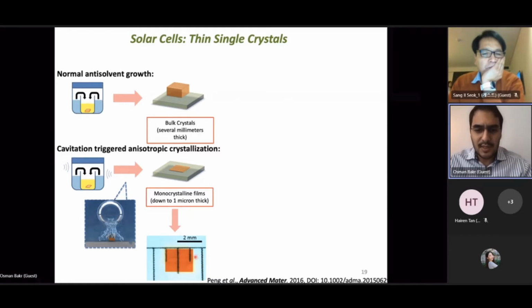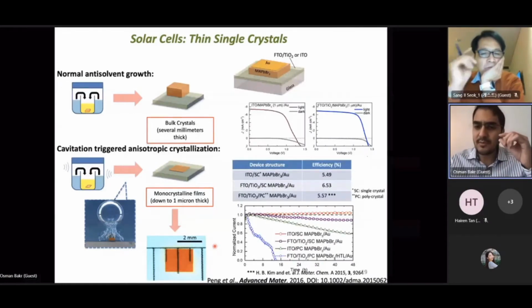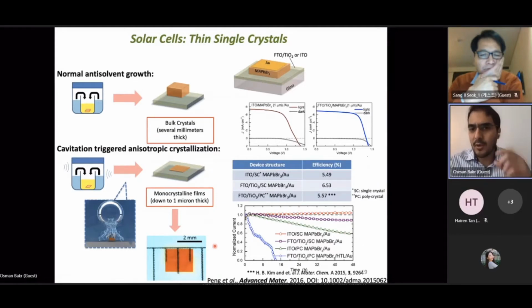And here's a crystal we grew that's a few millimeters in lateral dimension, but it's only a few hundred nanometers in thickness. And at that time, we fabricated the first thin film single crystal, monocrystalline perovskite solar cell. And at the time, it wasn't very efficient because we were only able to grow the crystal from a wide gap material. But it was really instructive for us because what we found is that you could still get a decent efficiency without using any hole transport material, and the efficiency was relatively stable in comparison to thin film polycrystalline solar cells. So this got us into the idea of growing single crystal perovskites.